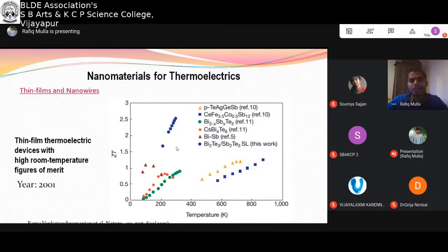Experimentally, in 2001, Venkatasubramanian reported a very high ZT value from a thin film. It was a bismuth telluride and antimony telluride superlattice thin film, where they produced about 2.5 ZT even in the year 2001 itself. But that thin film was very, very thin and requires a special technique to fabricate such superlattice thin films. But the fact is, the enhancement in ZT value is possible with such thin films.